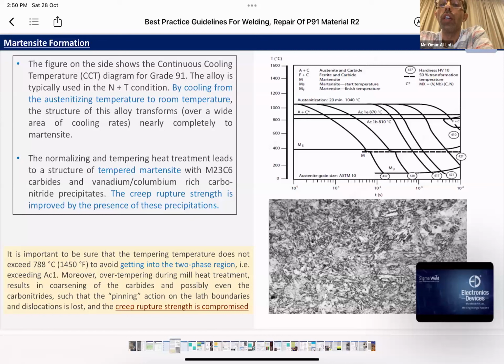So the tempered martensite has a better creep resistance and a better creep rupture strength for this material. It is important, again, to be sure that the tempering temperature does not exceed the lower transformation temperature AC1, which can affect the creep rupture strength of the material.